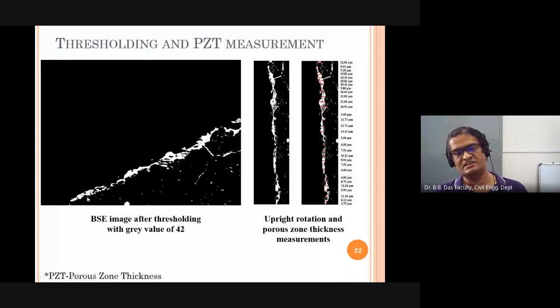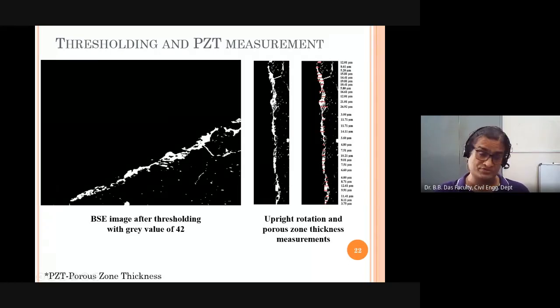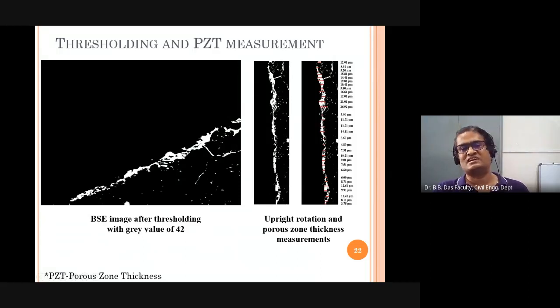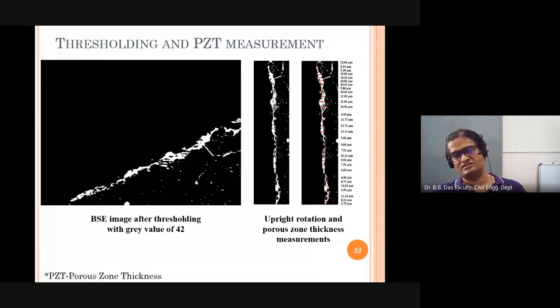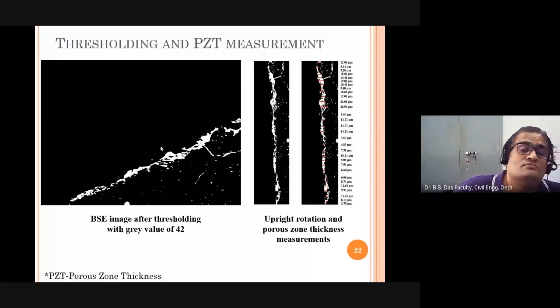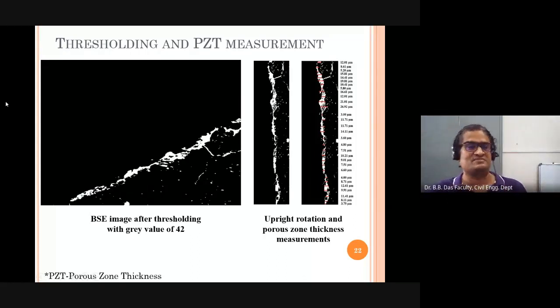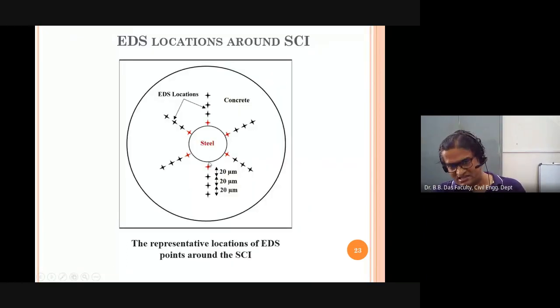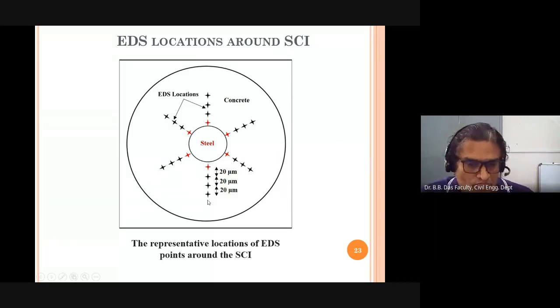In this picture you can see one point is on the ITZ, and then 20 micrometer, again 20 micrometer, again 20 micrometer, because we know this concrete is non-uniform or non-homogeneous. So it is necessary to check what is happening from the ITZ towards the concrete, because steel we know is very much uniform. From a metallurgical point of view something can be done, but from a civil engineer's point of view, nothing can be done, so it is better to measure this side. That is where the energy dispersive spectroscopic points were decided.